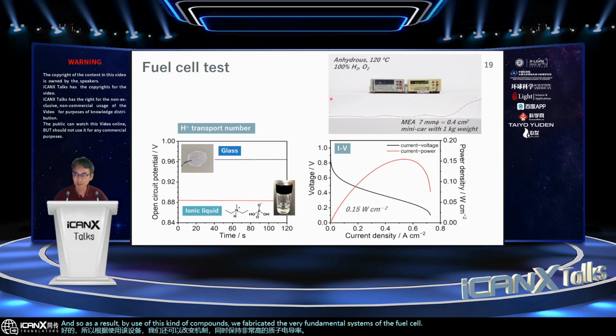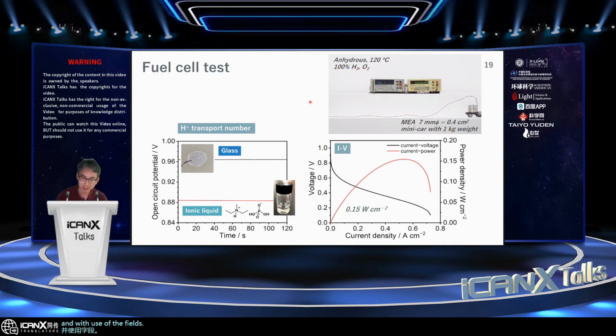The fuel cell is very popular, but it is still quite difficult to get good performance under completely anhydrous conditions, which means the humidity is 0 and the temperature is above 100 degrees C. This case is a very small fuel cell-based vehicle, but actually this small vehicle has 1 kilogram of weight on top. And with the fuels, this works very well with our metal organic framework glasses. And this IV curve is shown here.